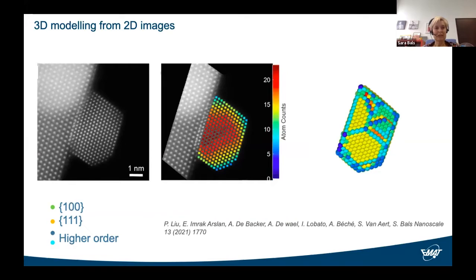And one of these alternatives is 3-dimensional modeling from 2-dimensional images. And so the idea is explained here for a gold nanoparticle sitting on a cerium oxide support. In this case, we only have one image available. And the first step is that we're going to quantify this image. Quantification in Antwerp is the field of expertise of my colleague Sandra van Aert and her team, and they are using what is called statistical parameter estimation theory to determine the positions of the atomic columns and to count the number of atoms in the atomic columns. And that is what is indicated by these color codes here.